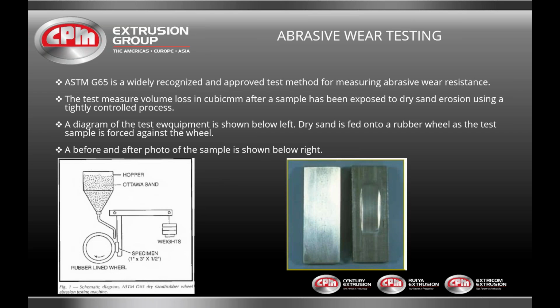The ASTM G65 is a widely recognized and approved test method for measuring abrasive wear resistance. It's more of a comparative wear resistance test, using dry sand. The test measures volume loss in cubic millimeters after a sample is exposed to dry sand erosion using a tightly controlled process. There's a diagram of the test equipment, where dry sand is fed into a rubber wheel as the test sample is forced against the wheel. A before and after photo of the sample is shown below right.